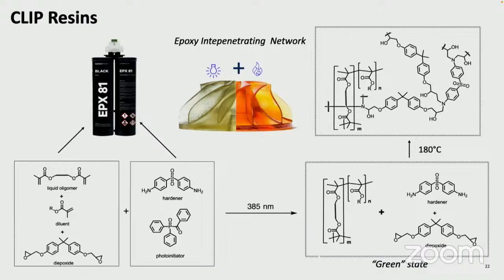And this orthogonal chemistry allows you to print the part. Now it's mechanically weak. It's 10 to 15% of a network and 85% of a step growth monomer, right? And all the forces are different. You have to control that with the software. But then you basically go through a solid state polymerization in the form of the part.